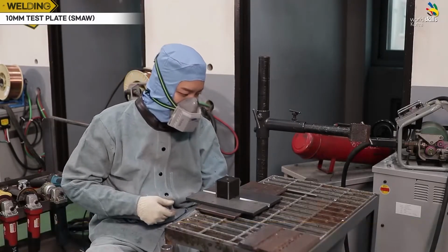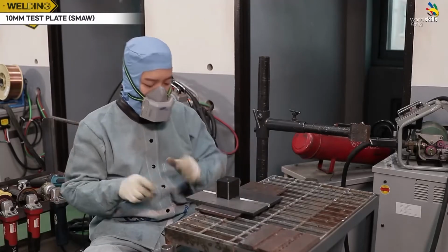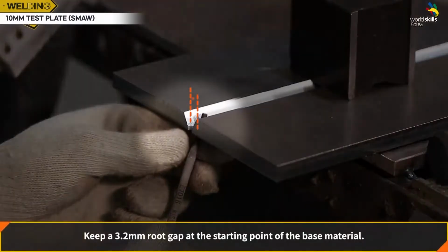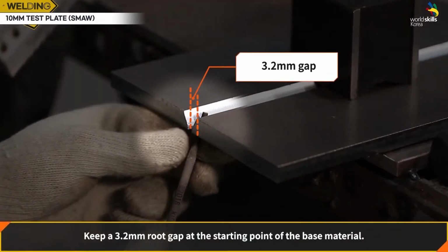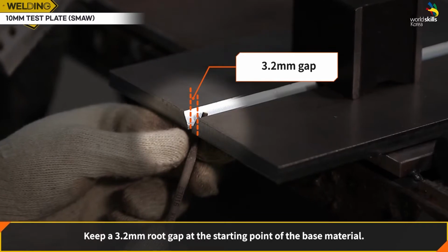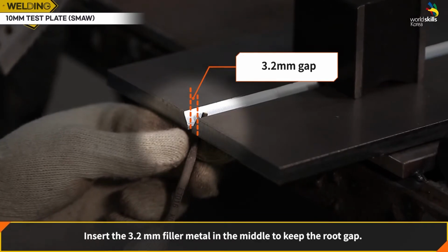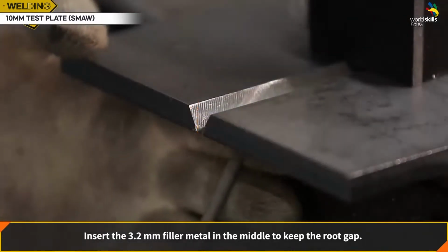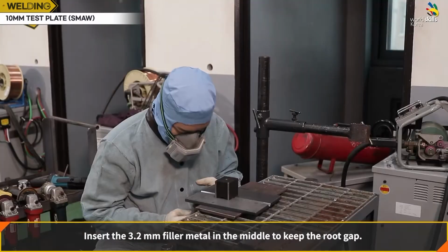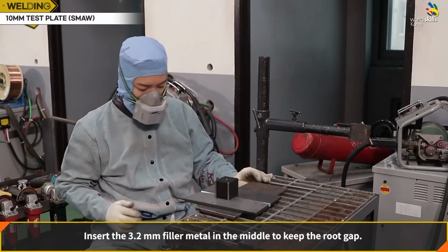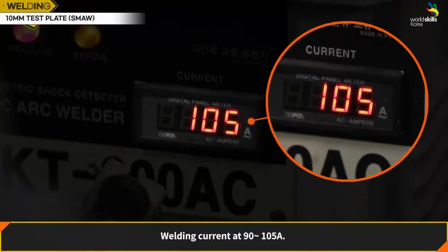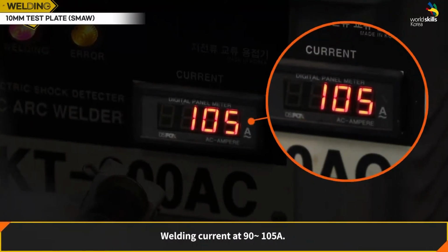After checking the misalignment, clear the space between the base materials. Keep a 3.2 mm root gap at the starting point of the base material. Insert the 3.2 mm filler metal in the middle to keep the root gap. Welding current at 90 to 105 ampere.